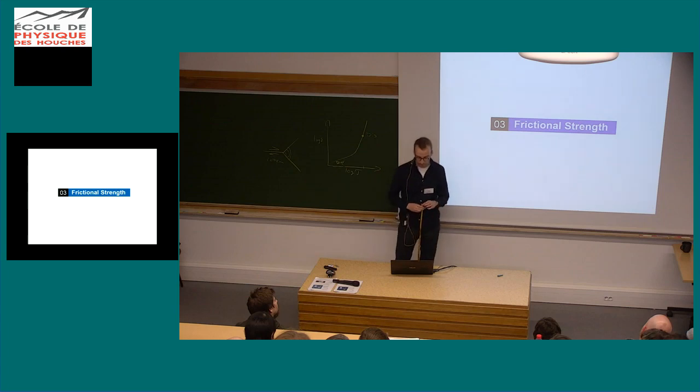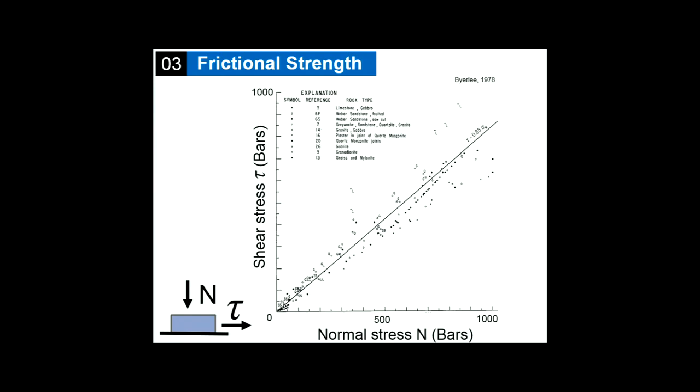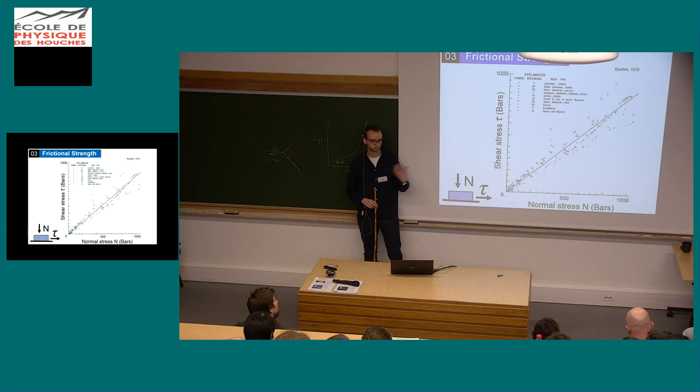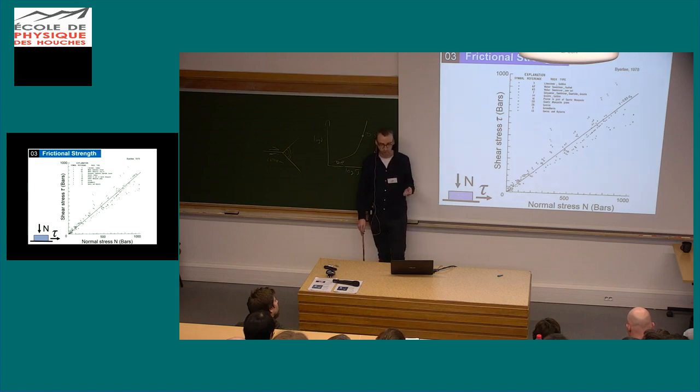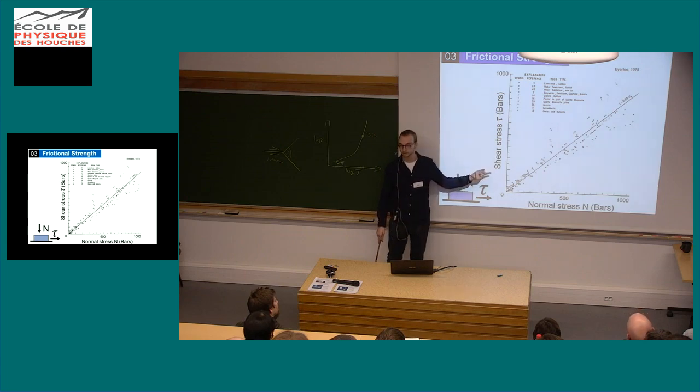That was the end of the first project. In the second one, I'm moving away from the hot stuff and investigating frictional strength of rocks. Back in the 1970s, Byerlee did a famous series of sliding experiments. He took natural rocks, put them on a table, let them slide with a known force, and found that no matter what material, all of them seem to have a coefficient of friction of around 0.6, independent of chemistry, independent of rock type. The problem is that if we try to run numerical models, stress inversions, slip analysis of natural fault zones and so on, we need a coefficient of friction of around 0.2 to make them work. So where is the discrepancy between what we see in those older experiments and what we require for our models?